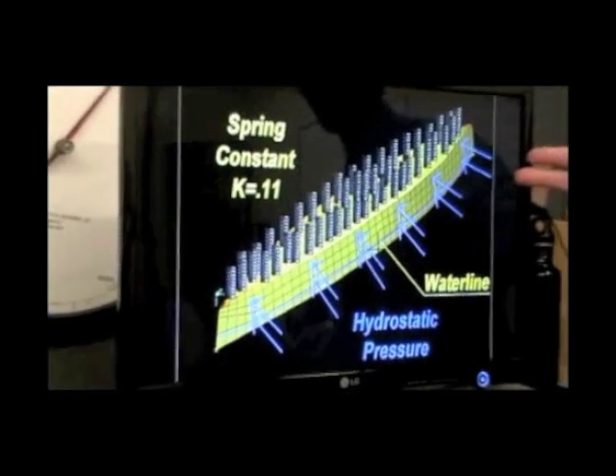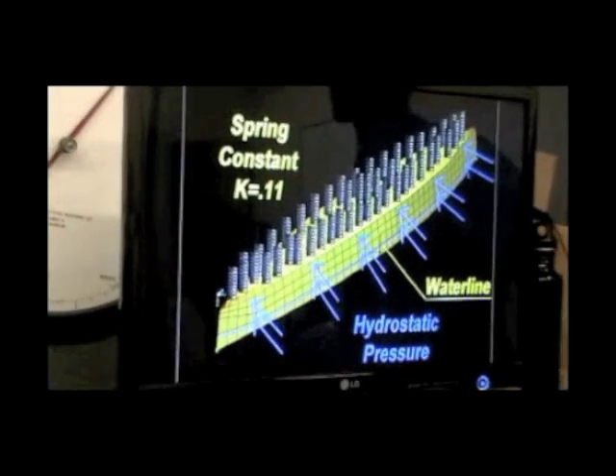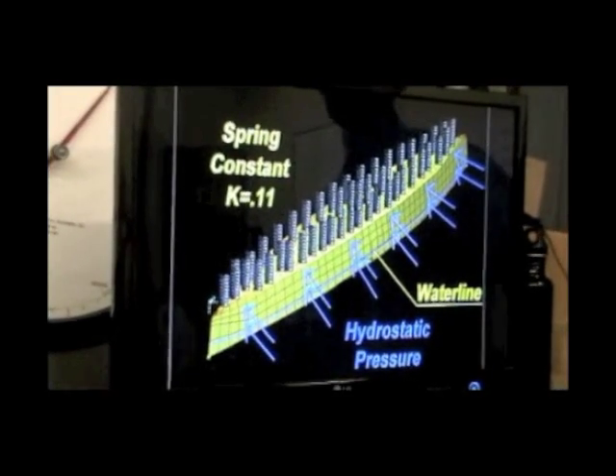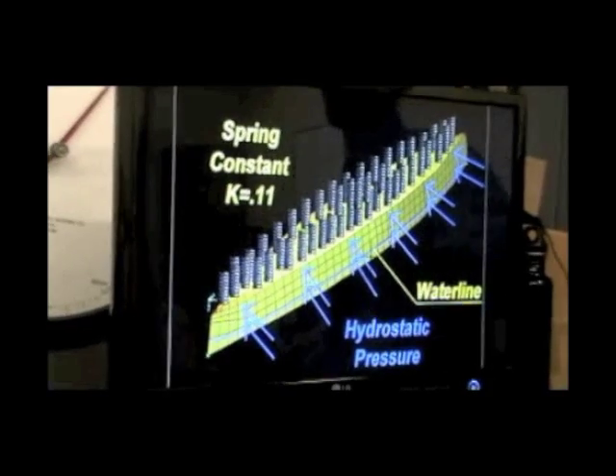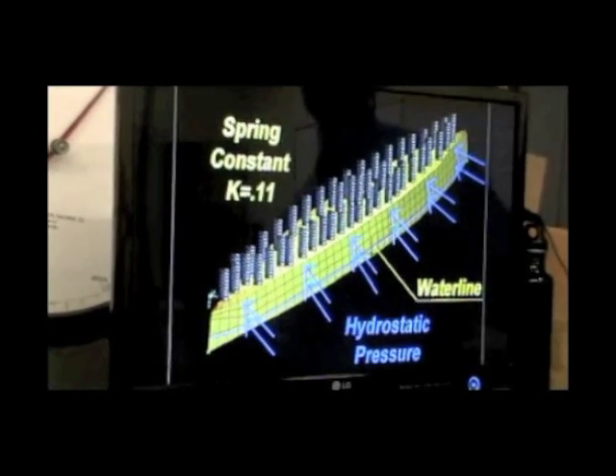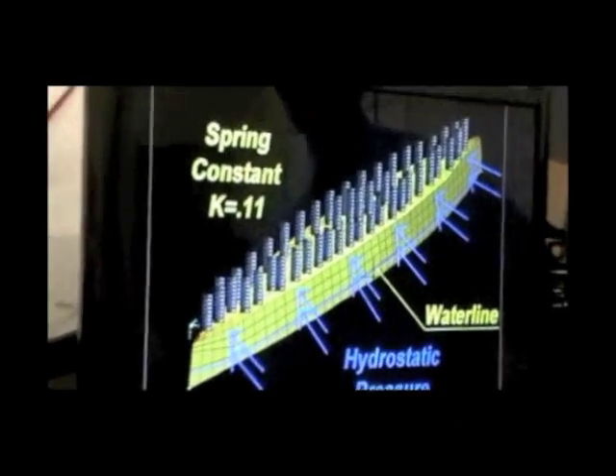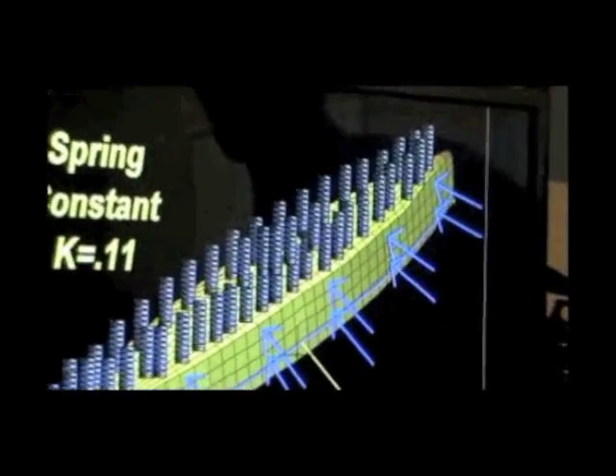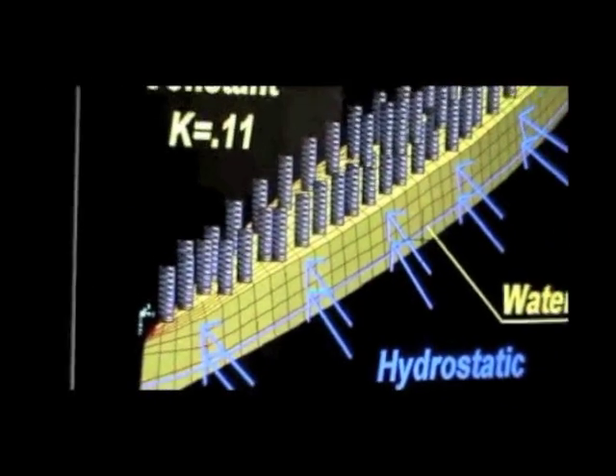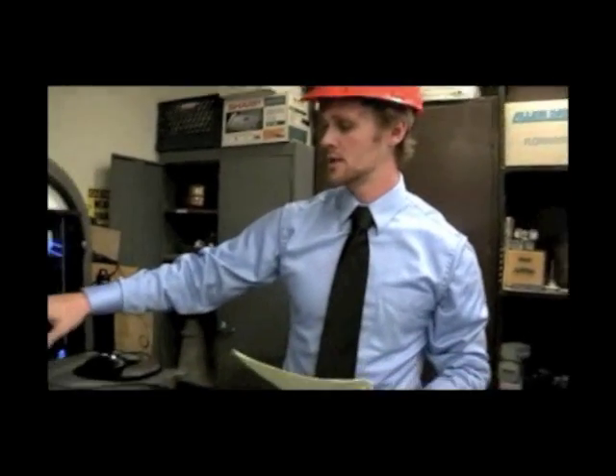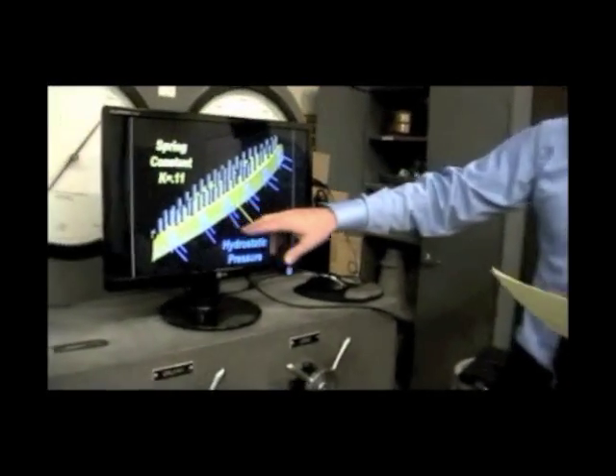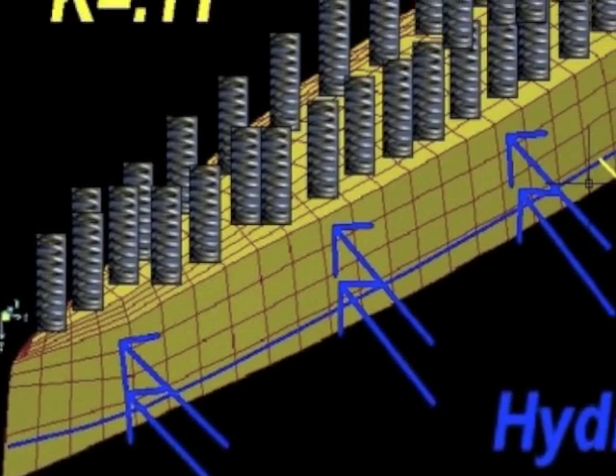The spring coefficient was determined using the force displacement of water and was distributed to 323 points along the bottom of the surface. We had to make sure that the springs were all equipotential to the surface, as well as the hydrostatic pressure. The water line is determined to be about 4 inches from the top of the rail. It extends all the way from the front of the boat to the back, or from the bow to the stern.